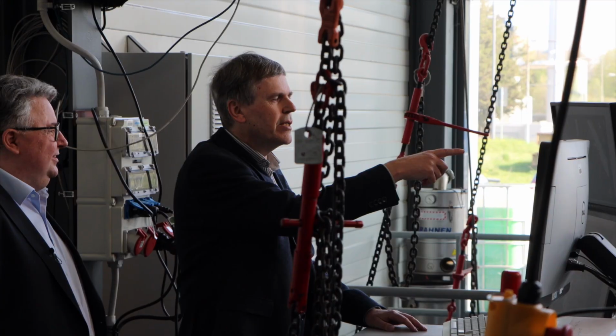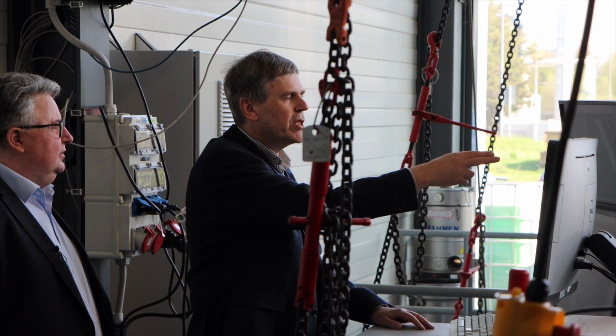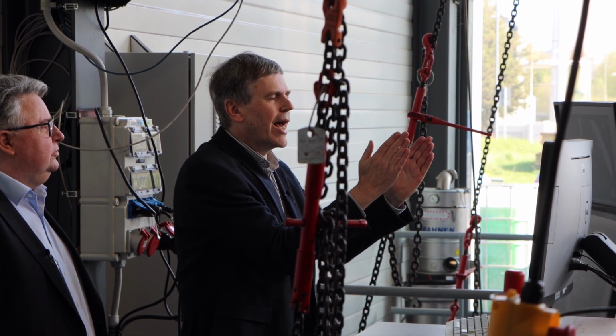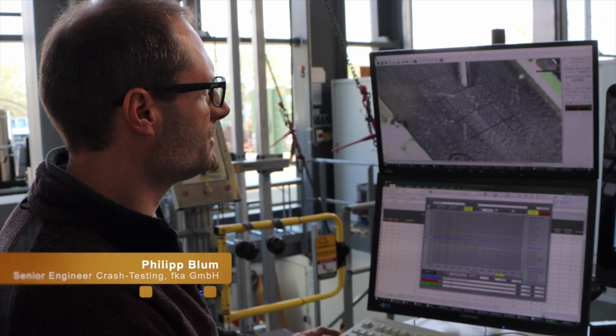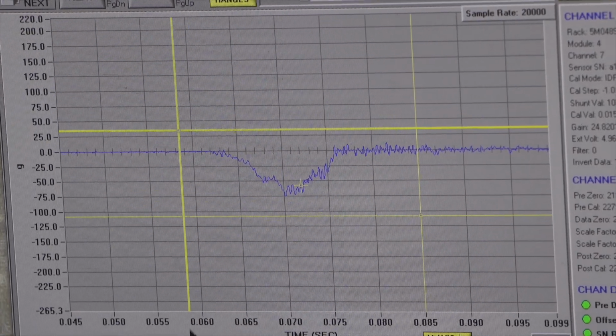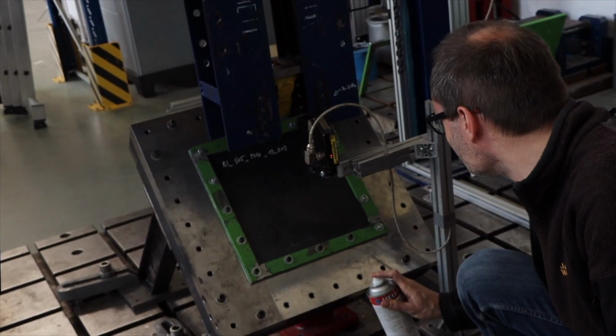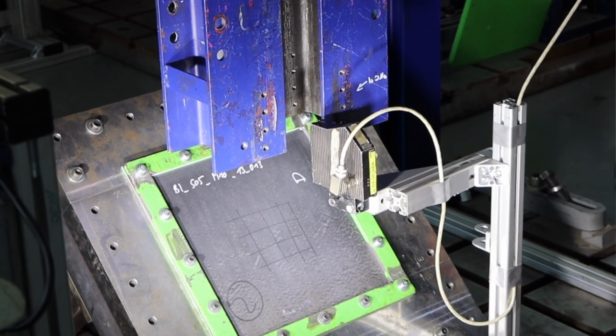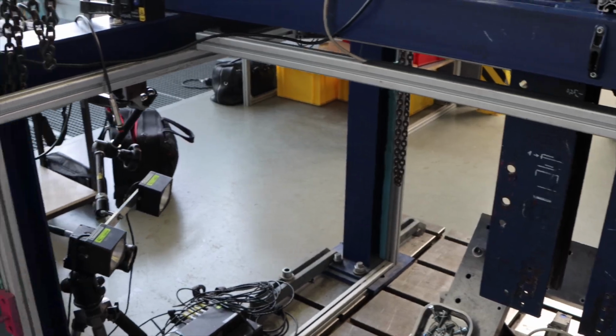And let me ask you the following, Philipp. What type of data do you collect? Of course, the speed of the dart at the moment of impact is measured, but that is already predicted by the drop height and the mass. But the most important for the material behavior is to collect the force deflection curve, and that's indirectly measured by an acceleration sensor. So mechanics is used there to calculate the force deflection curve. On the force deflection curve, you can also see when you have first fracture of the material. So it's very good to estimate how much energy is absorbed inside the material until the moment it fractures. Apart from that, high-speed video is also taken, so that you can correlate it to specific modes of fracture that you observe.